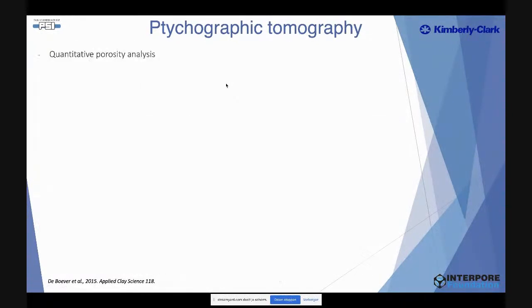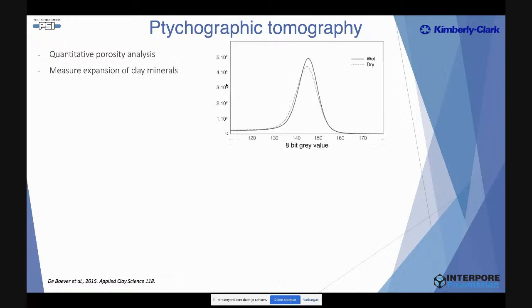And this in a non-destructive way. So with this technology, you can go for high resolution quantitative porosity analysis, but on limited volume, of course. But it also allows you to control the conditions around your sample. So we were measuring, for instance, the expansion of clay minerals, and we were scanning it in a wet condition and in a dry condition, and we were seeing how these clays were behaving.